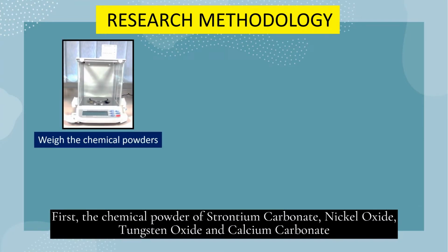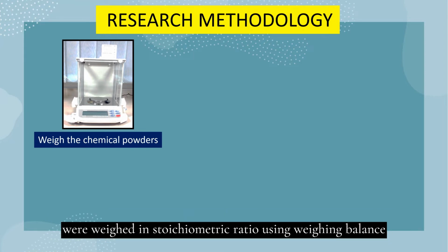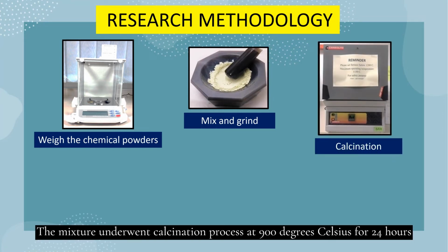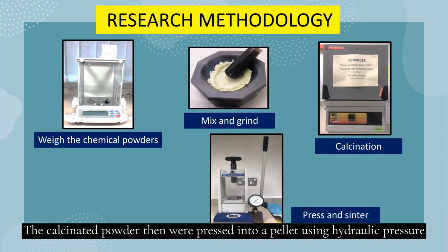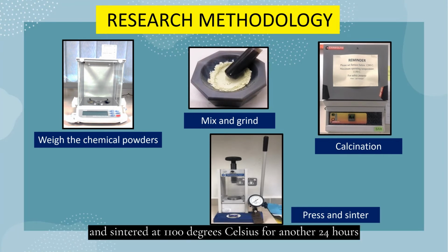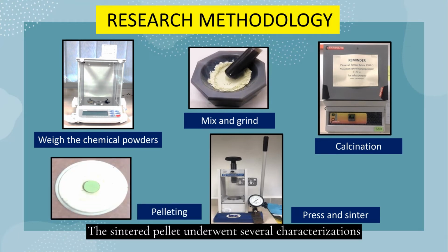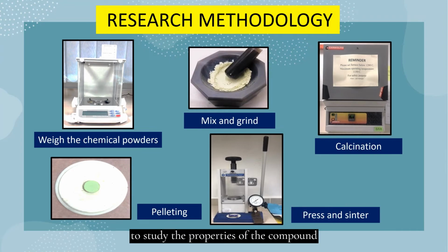The method used to synthesize the compound is solid-state reaction. First, the chemical powders of strontium carbonate, nickel oxide, tungsten oxide and calcium carbonate were weighed in stoichiometric ratio using a weighing balance. Then, the mixtures were ground using agate mortar and pestle for about 2 hours until homogeneous. The mixture underwent calcination at 900 degrees Celsius for 24 hours. The calcined powder was then pressed into a pellet using hydraulic pressure and sintered at 1100 degrees Celsius for another 24 hours. The sintered pellet underwent several characterizations to study the properties of the compound.